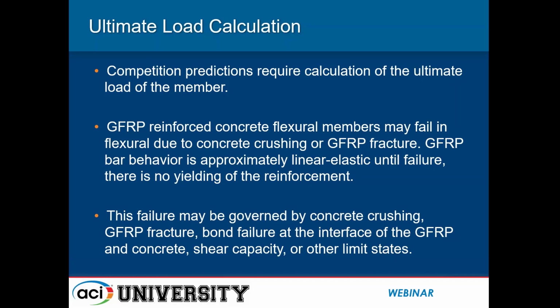There are other failure modes that we have seen at the competition. So not only have we seen GFRP concrete crushing in a flexural failure or GFRP fracture due to a flexural failure, but we've also seen bond failures at the interface of the GFRP bar and concrete. We've seen shear failures, and we've seen other limit states as well. So it may be to your benefit to predict ultimate load based on different failure modes, including bond, flexural behavior, as well as shear behavior.